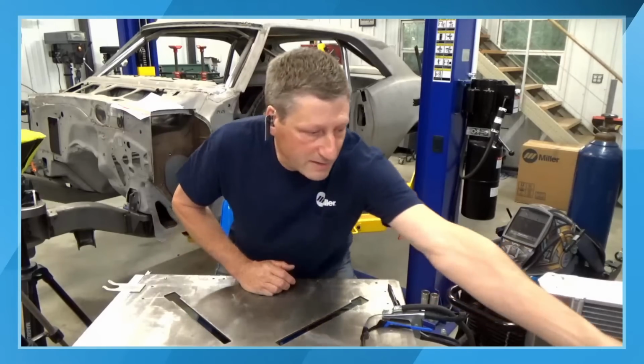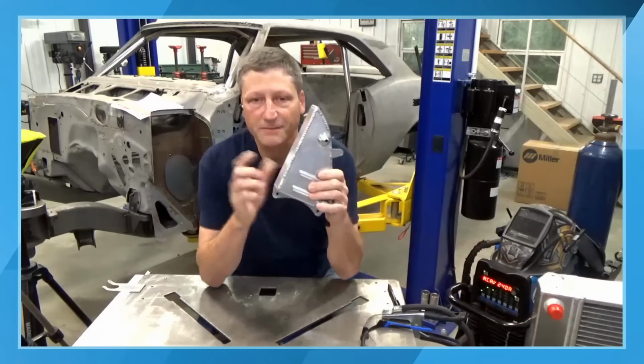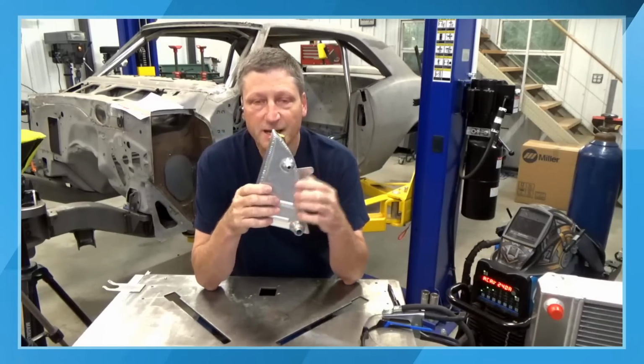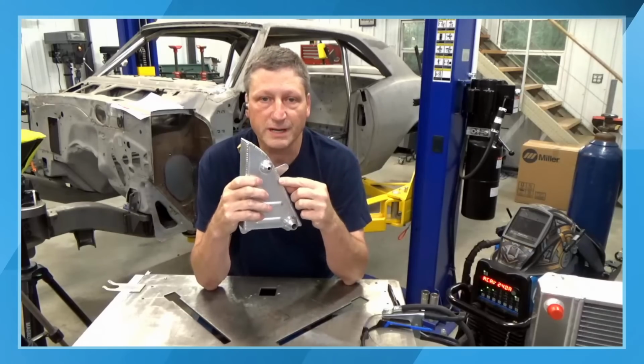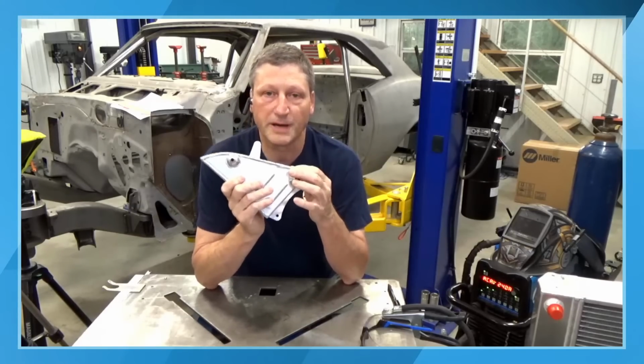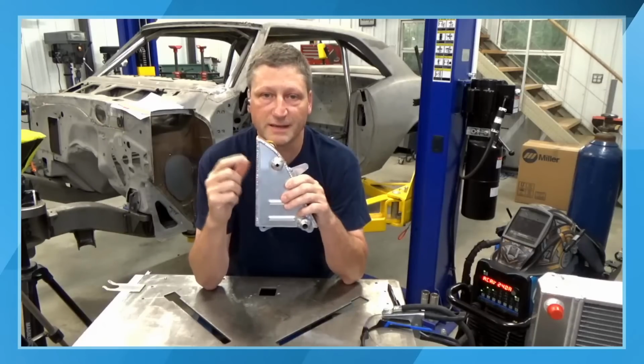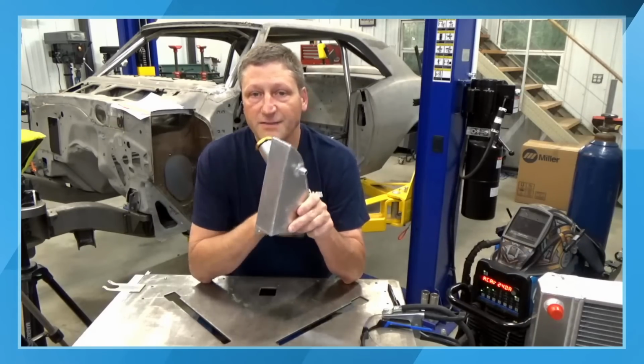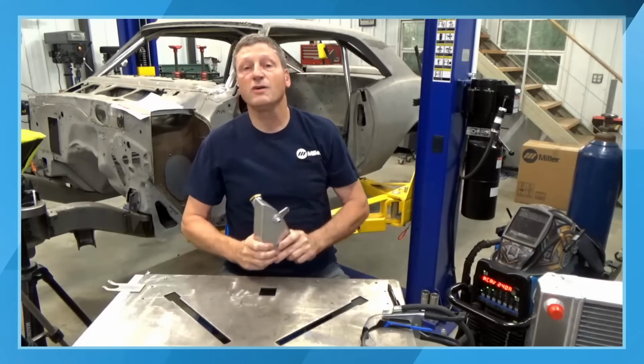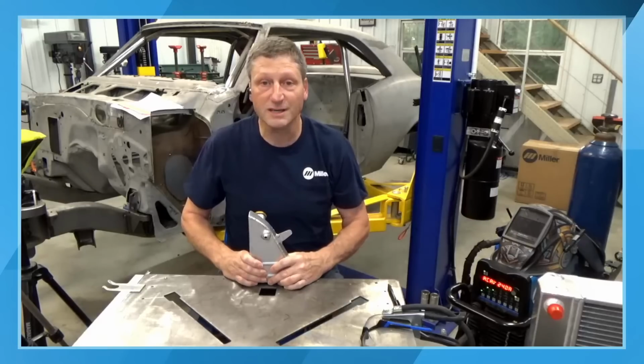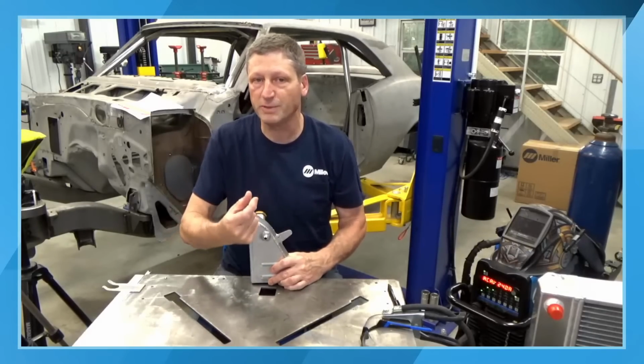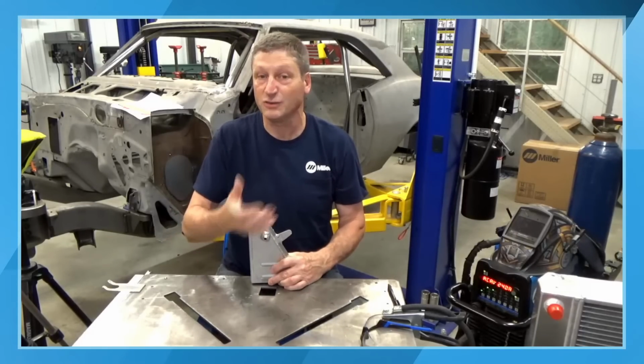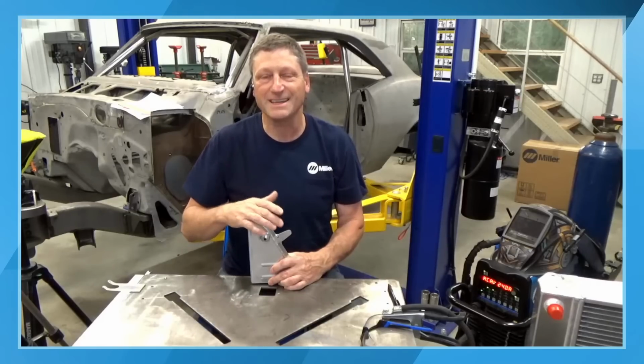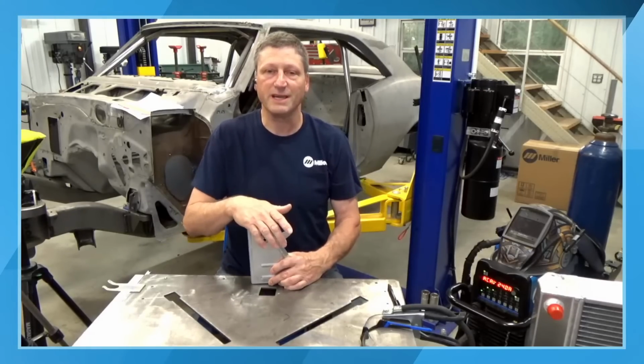So when I make these tanks, this is 3003, I'm using a 4043 or a 4943 filler metal because they're suited for high temperature applications. The 5000 series, even though they typically look nicer and give you a shinier weld puddle after you're done welding it, so they look good, it's not suited for a high temperature application.